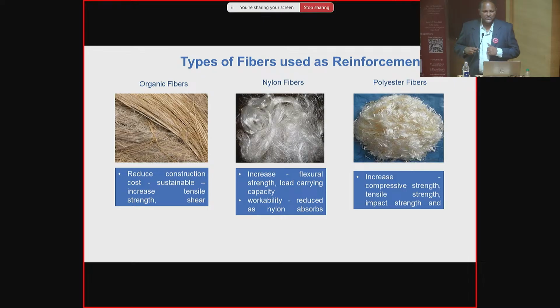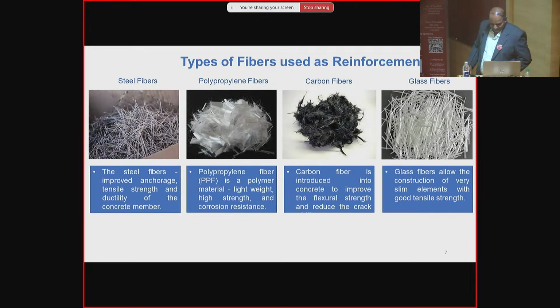Even sometimes fibers are used to reduce the shrinkage of the concrete. You might have seen, for a larger horizontal slab concrete, during peak summer time, once you lay the concrete, within 4 to 5 hours you can see cracks popping up on the top of it. It is due to shrinkage, that is called plastic shrinkage. To avoid that, you can use these kinds of fibers so that they take care of the stresses developed. So each one has its own purpose. This has to be kept in mind, right?